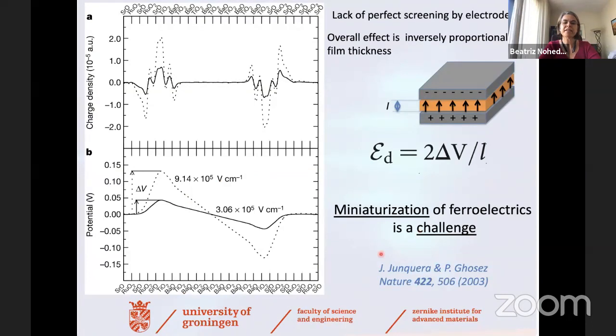As explained in this classical paper by Javier Junquera and Philippe Ghosez. Of course, a way to solve this problem, you could think, would be to put electrodes on your ferroelectric, and because the electrons in the metal will screen the polarization charges, you expect that these depolarization effects will not be there. But that's actually not true, because in real life there's no perfect metal that can screen perfectly the polarization charges.